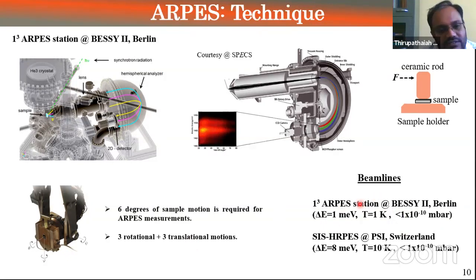And these are the beam lines. At 1 cube ARPES, you have 1 meV energy resolution, and the temperature you can go down to actually below 1 Kelvin, and the vacuum chamber is always better than 10 to the power minus 10. And at SLS we have this high resolution beam line, and here you have approximately 8 meV with the sample temperature less than 10 Kelvin, or quite close to that. And it's always, I think, high 10 to the power minus 11 pressure.